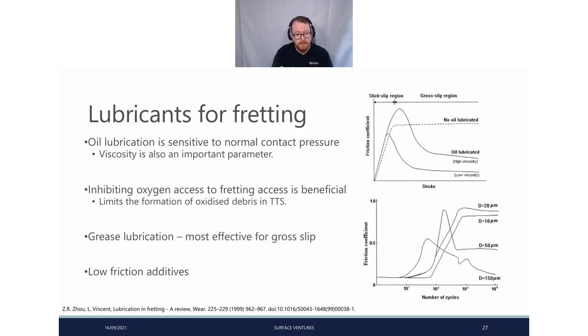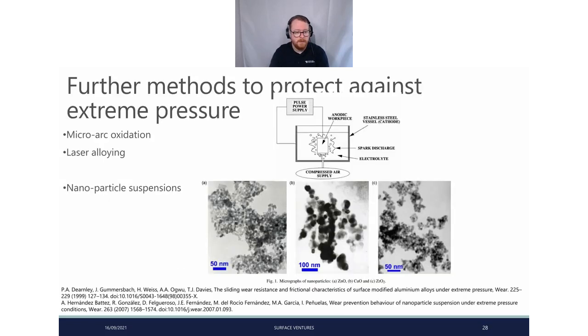Lubricant is also great because it can inhibit oxygen access to this, which can also reduce the amount of oxygenated debris. For gross slip, grease lubrication is most important. When we have different displacements here, we can see how the coefficient of friction changes for a different number of cycles, and low friction additives, things like MoDTC, can be quite good. Other methods protect against extreme pressure. Micro-arc oxidation, so making the surface harder, laser alloying, and there's been a little bit of work to show that some nanoparticle suspensions can be quite good, specifically against some extreme pressure scenarios.